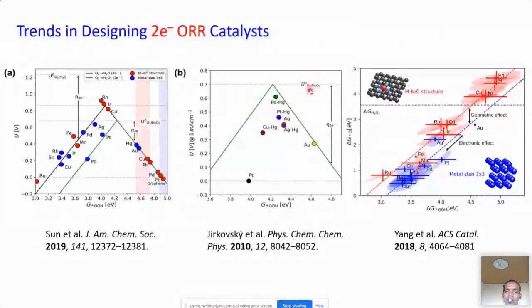The production of hydrogen peroxide via oxygen reduction can be achieved by diluting the catalytic site in an ORR inert host material. And very recently, Yang compared the free energy of hydroperoxide intermediate formation with oxide intermediate formation, and they found that the M-N-C catalysts of these 4 materials are very highly active for selective 2-electron reduction, which can produce hydrogen peroxide efficiently.